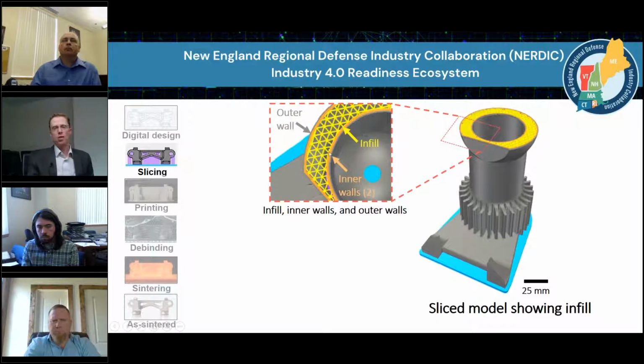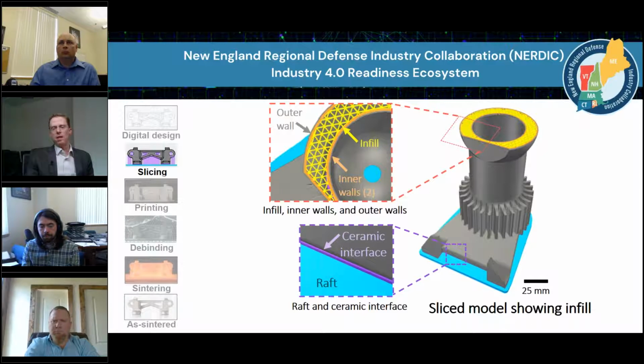In this case, there's a total of 3 outer layers: the outer wall with 1 layer and 2 inner walls shown right here, so 3 walls right at the outside edge. The infill comprises a hollow with an infilled center section. At the bottom, these parts are built upon a raft, shown in the slicing as blue. There's a ceramic interface that separates the raft from the desired part for the sintering process. Otherwise, the raft would sinter to the desired part. The ceramic interface is shown as purple between the outer wall of the part in gray and the raft.